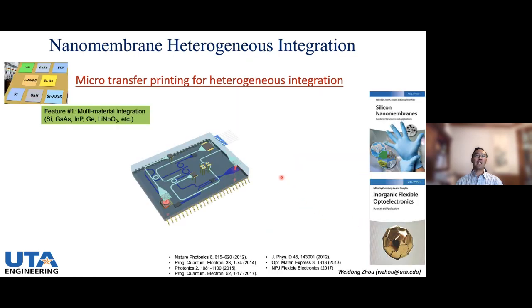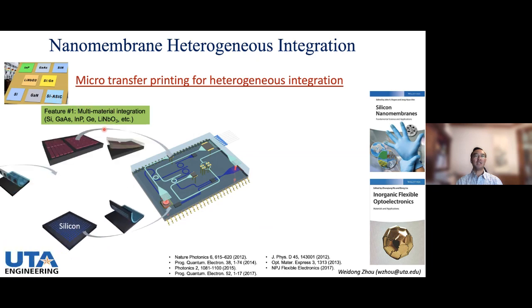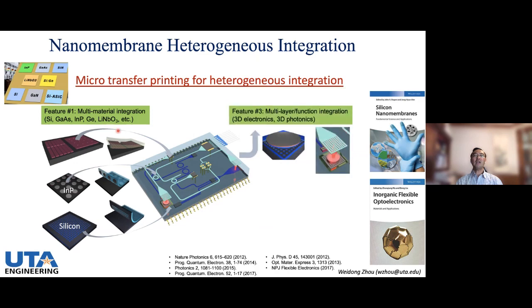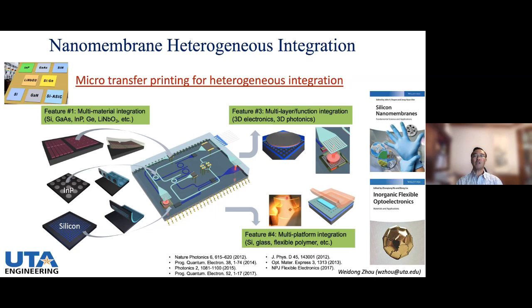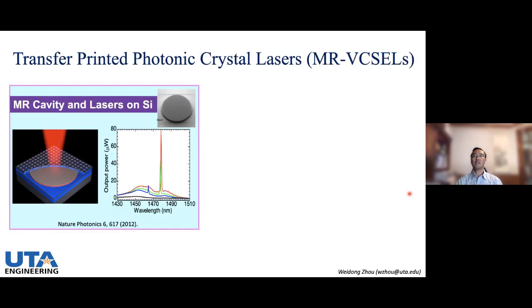With this in mind, you can now put many different materials together. You just peel off different pieces of functional layer and put them onto the same silicon or any substrate. So, multi-material integration. Then you can do multilayer stacking, layer by layer, putting different layers on top of each other. And finally, you can put them on a flexible substrate as well, or glass or polymer. So it's very powerful. Here, just showing some book chapters we contributed to, talking about this membrane process for integration, either for silicon-based electronics or photonics, or for flexible optoelectronics.